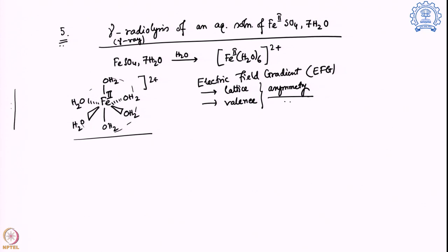Why? Because this is an octahedral geometric system, so my d orbitals will split into Eg and T2g symmetry, and as we have discussed earlier, the ligands can be explained as sigma donor, pi donor, sigma donor only, or sigma donor pi acceptor, and depending on that, the energy gap between them is going to split, which is known as delta octahedral, or crystal field splitting energy, or ligand field splitting energy. This depends on the quality of the ligand and which atom is coordinating to the metal. Over here oxygen is binding, which is group 16, so it is a sigma donor pi donor, which ensures that this Eg and T2g gap is quite low. That means it prefers a high spin system.